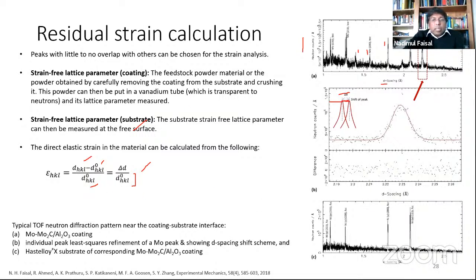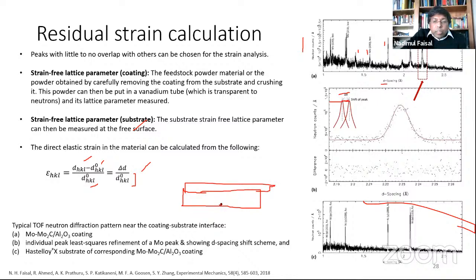For the substrate, suppose this is your substrate and you are spraying on top of it. You can take this point as your d naught, or you can take an unsprayed substrate and measure d naught anywhere. So there are different ways to do it. For coating, you can take the coating off, crush it into powder, put it into a vanadium tube and get the d naught. So that is something you have to plan before the start of the experiment.